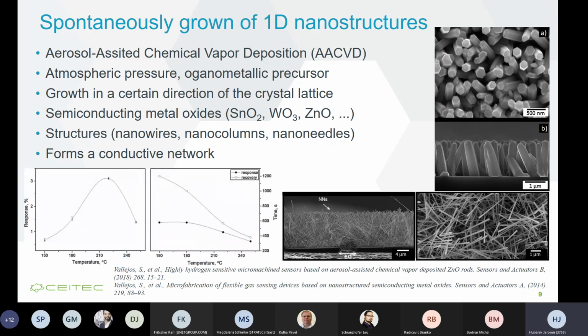So we obtained, for example, a higher response to gases, and also a lower working temperature, where the sensitive films are more sensitive to the gas. So it was a significant decrease of the temperature.